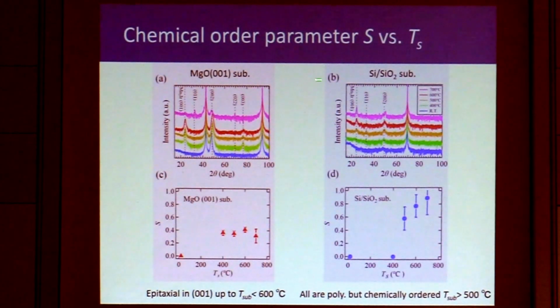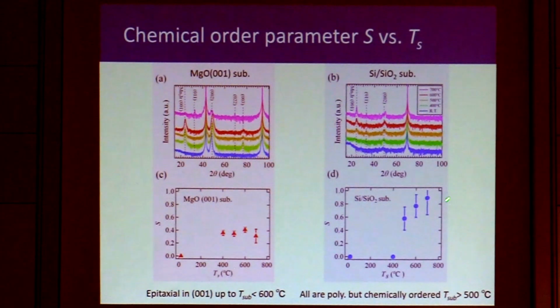Here we compare the manganese 3 iridium on the MgO 001 substrate and on the thermally oxidized silicon substrate. Of course, on the MgO 001 substrate, we have epitaxial manganese 3 iridium because the lattice constant is not that far. However, when we heat up to 700 degrees C, this epitaxy gets destroyed. However, as you can see from the 001 superlattice peak, even for the non-epitaxial case, we still have L12 ordered manganese 3 iridium. For the silicon oxide case, we don't have epitaxy here, but as we increase the substrate temperature, we start to see the chemical order. So this is polycrystalline.